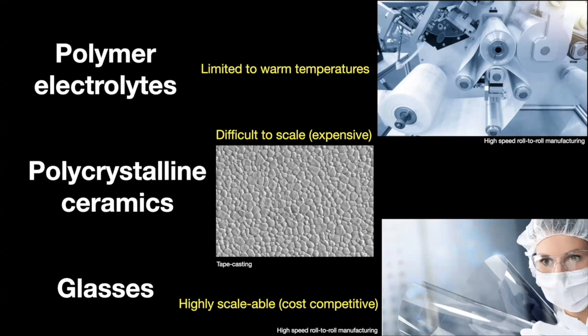You couldn't quite do that with sulfides because they need to be protected from the atmosphere. But once you get below about 100 microns, glasses can be processed in a roll-to-roll fashion. So they are scalable and they have been scaled, right? There's an entire industry globally to do this. So they have that advantage.